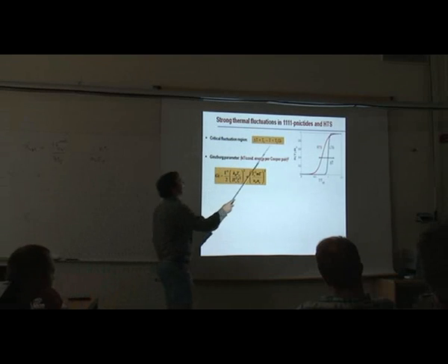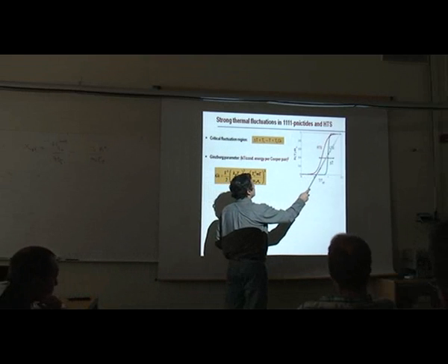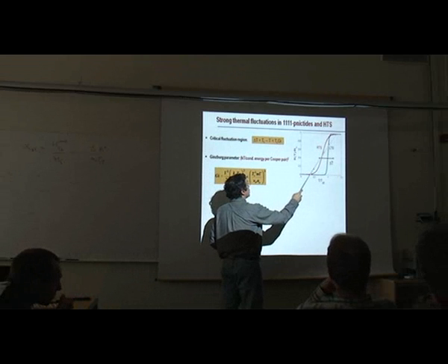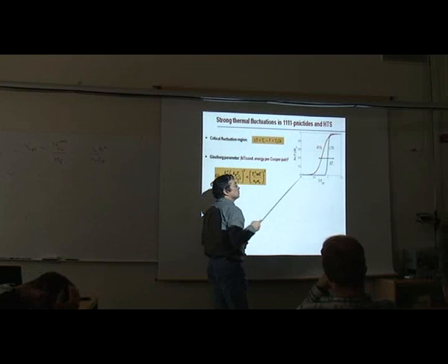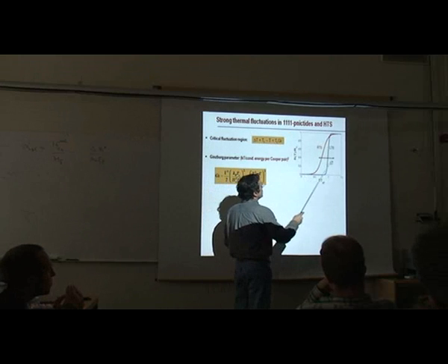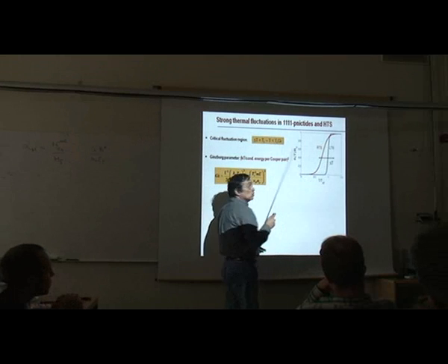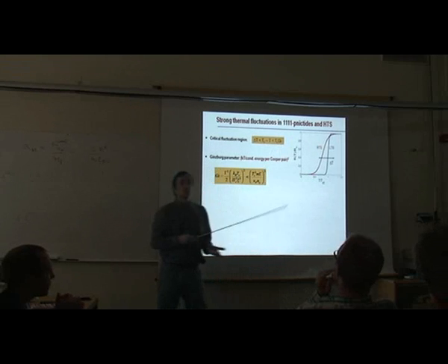This Ginzburg number also defines the width of the resistive transition due to fluctuations. So if fluctuations are zero, then we just have an ideal sharp transition: normal state here, drops to zero, and then zero here. With the account of thermal fluctuations, the transition is broadened, and the width of that transition is proportional to the Ginzburg number times Tc.